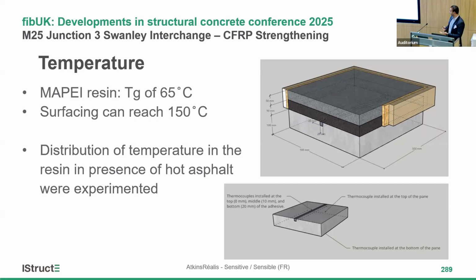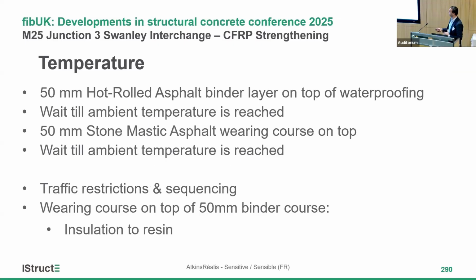Then after 24 hours, a hot rolled asphalt. Before laying that, we had thermocouples installed on top of the resin, center of the resin, and at the bottom of the resin. Then a layer of waterproofing was applied, and one more thermocouple was installed on top of it. And then a 50 mm hot rolled asphalt on top of this waterproofing layer.